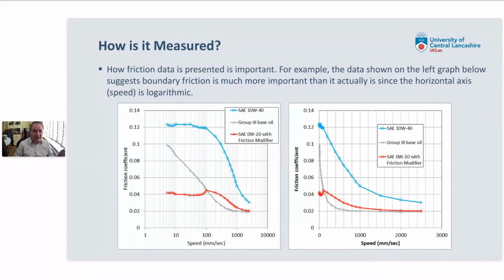One thing that is worth commenting on, though, is that it's important to consider how to present the results from these machines. On the left-hand side, we've got the results as usually shown on a logarithmic scale. To someone who's not familiar with this type of work, you get the impression that the boundary friction regime is really, really important, because almost half this graph is boundary friction, between a speed of about 5 millimeters per second up to about 100. And then the mixed regime doesn't seem quite as important because it's squished on this graph because of the nonlinear logarithmic scale that we used.